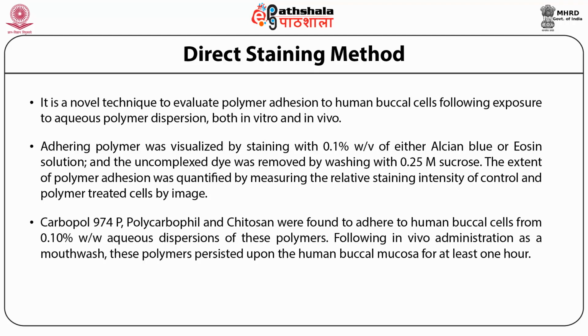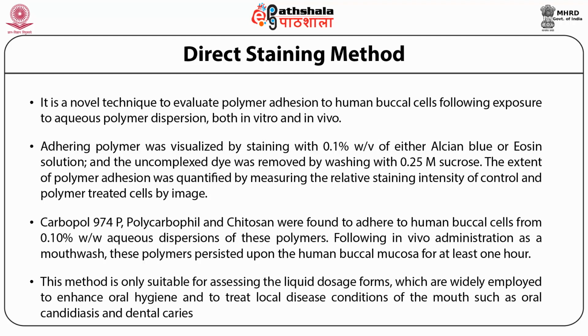0.10% weight by weight aqueous dispersions of these polymers. Following in vivo administration as a mouthwash, these polymers persisted upon the human buccal mucosa for at least 1 hour. This method is only suitable for assessing liquid dosage forms, which are widely employed to enhance oral hygiene and to treat local disease conditions of the mouth such as oral candidiasis and dental caries.